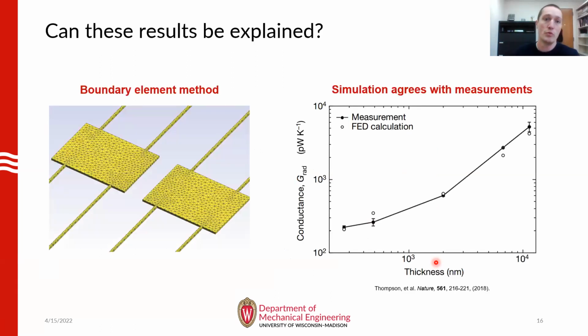To answer the question, we again relied on our FED formalism, which we implemented using a boundary element method, which you can see illustrated on the left. That allowed us to simulate the exact geometry of our membranes. From that, you can see the plot on the right, where the predicted conductance based on the FED framework agrees quite well with the measured results for each thickness. So clearly, the measured results do make sense under the FED framework. The question then becomes, what's the mechanism?